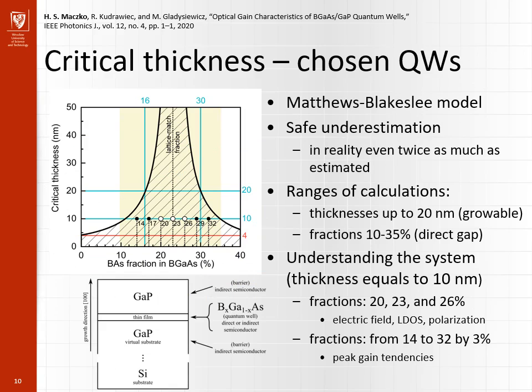Within this fraction range, the critical thickness calculated based on the Matthews-Blakeslee model is almost always greater than 10 nanometers. This model underestimates the critical thickness, so calculations for thicknesses twice as great are still reasonable. Therefore, the chosen ranges of calculations are the range of fraction where boron gallium arsenide is a direct gap material and the range of thicknesses up to 20 nanometers.